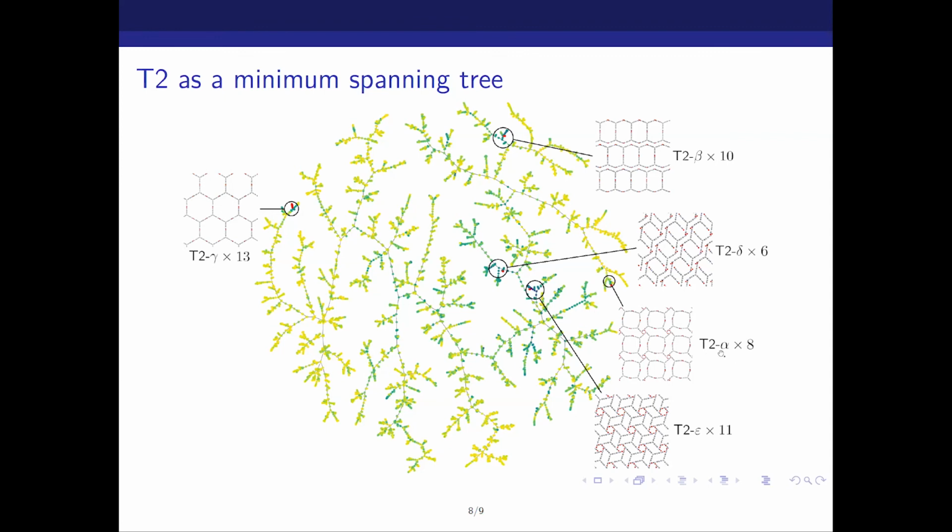These numbers by the names of the structures, by the way, say times 8 or times 11, is the number of matches it found. And I declared a match as packing similarity, giving you basically an exact match. So in this case, we've managed to place our experimental structures next to their nearest neighbors out of all of T2. And this didn't take particularly long to produce.